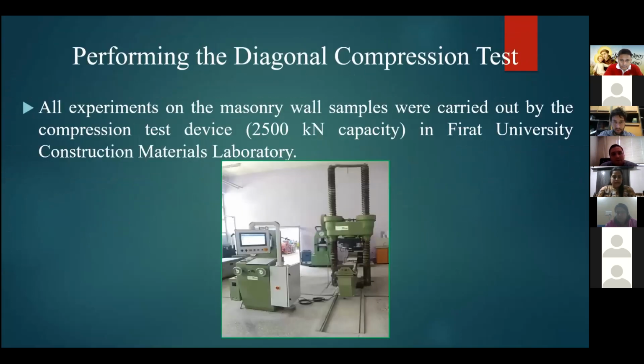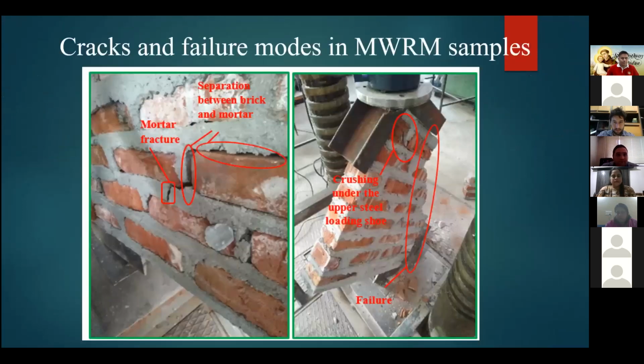All experiments on the masonry wall samples were carried out by the compression test device in Fırat University Construction Materials Laboratory in Turkey, shown in the figure. Cracks and failure modes in MWRM samples. Figure 1, mortar fracture and separation between brick and mortar. Figure 2, crushing under the upper steel loading shoe and failure in MWRM samples.